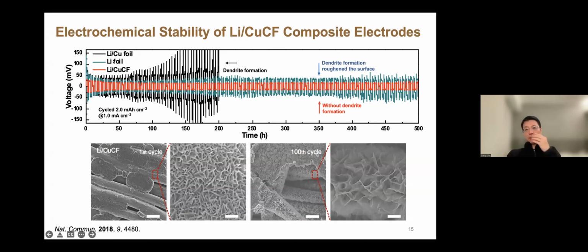If you compare to the lithium foil and lithium metal deposition on top of foil, there's huge dendrite formation and instability over the cycling process. So we were very happy at that time, right? Because we didn't do too much of experiment, and we observed this phenomena.